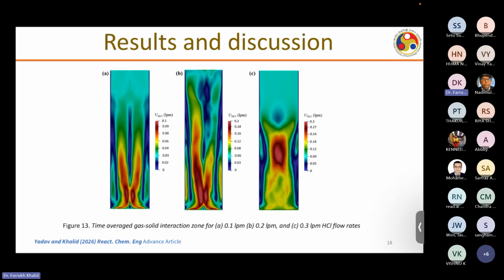We found that if the speed of the HCl gas is very high, because it's liter per minute, so basically it's HCl gas velocity, then the residence time of the interaction between the aluminum particle and this HCl gas is very less. However, the mixing is really good. In the case when the velocity of HCl is less, the mixing is not that good, but HCl has more time to interact with the aluminium particles.